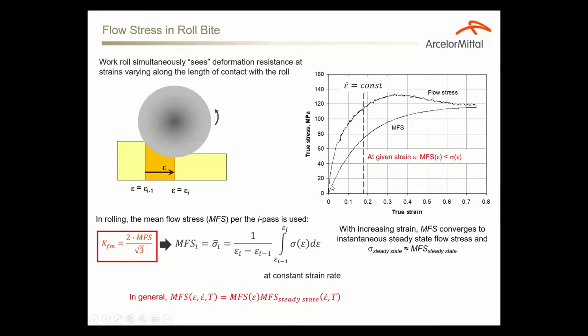The mean flow stress is a function of strain, strain rate, and temperature. During hot deformation, the instantaneous stress basically attains a steady state value, which with increasing strains becomes strain independent. We found that the mean flow stress at high strains converges with the instantaneous flow stress. That's a very convenient property of mean flow stress, so that we could use instantaneous stress values to approximate mean flow stress. We don't need numerical integration of the flow curves all the time. And then we can translate it into deformation resistance KFM values that the mill models are using for their operations.